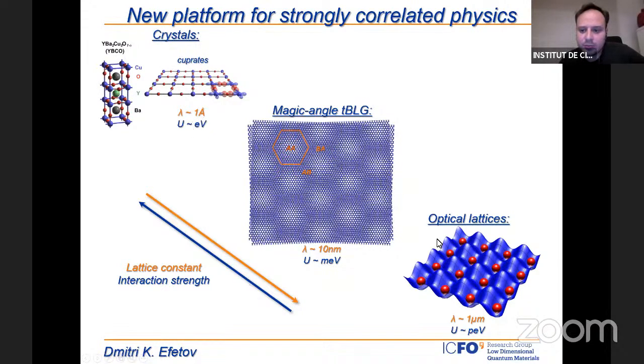The other known systems to form Mott insulators are optical lattices. Here the unit cell is much bigger, on the order of microns, and the interaction energy is on the order of pico-electron volts. And then twisted bilayer graphene is somewhere in between. It has a much bigger unit cell than crystals, but smaller than optical lattices, and therefore the interaction energy is also intermediate, on the order of milli-electron volts. I will talk in a second about what kind of new possibilities this opens up.